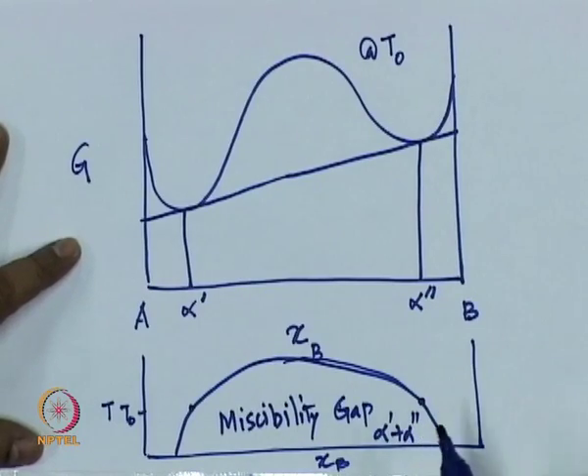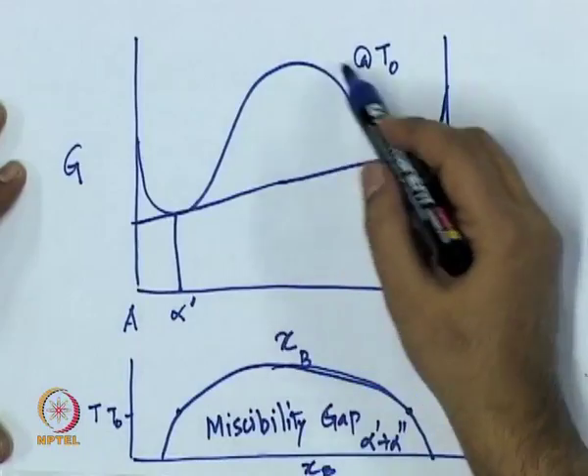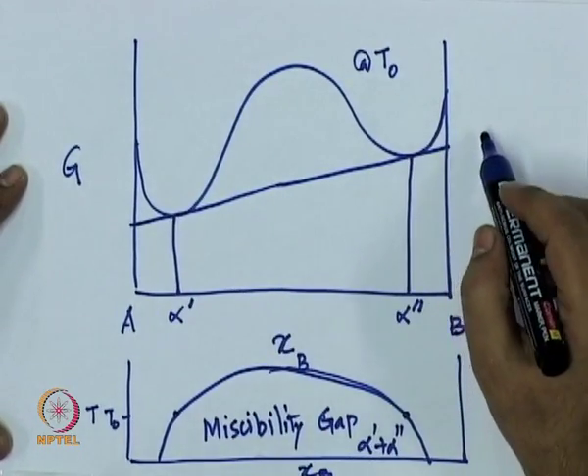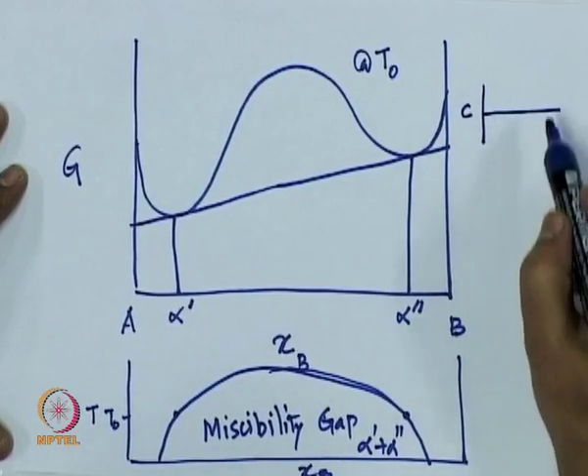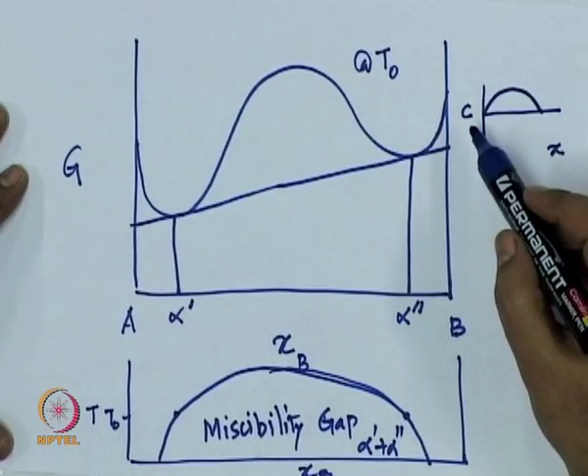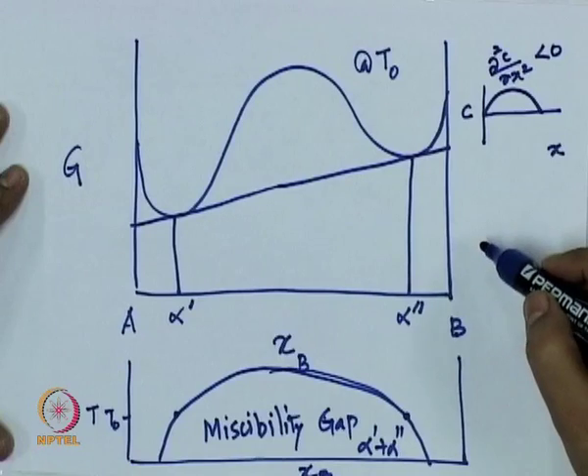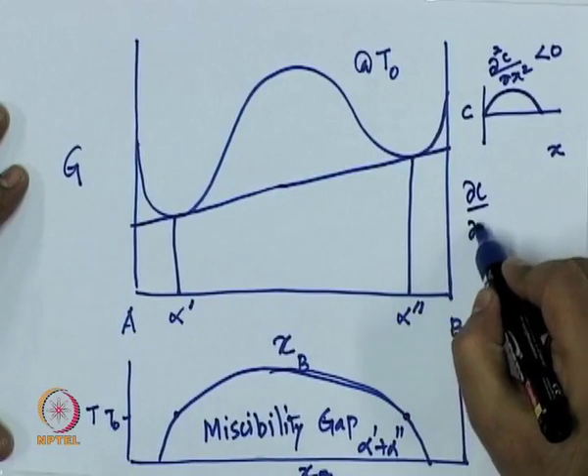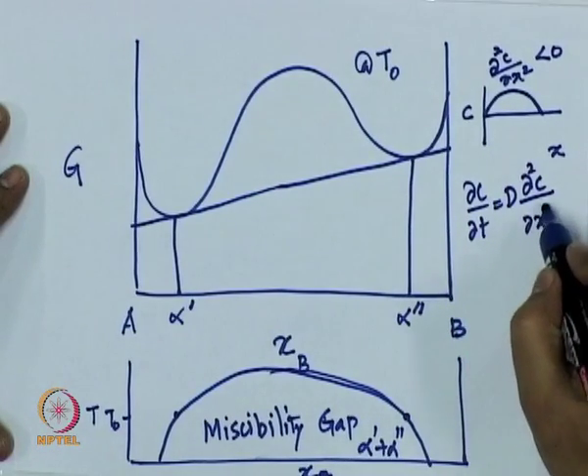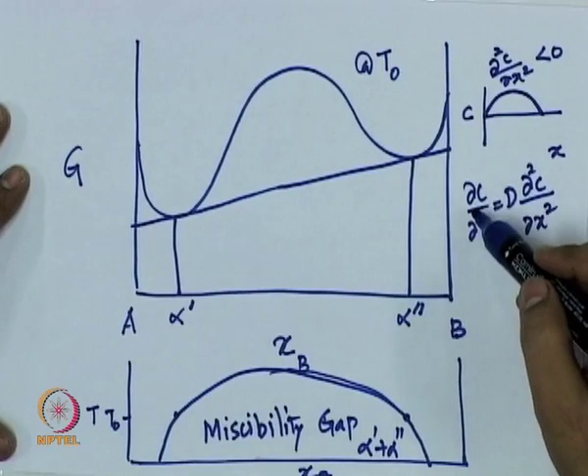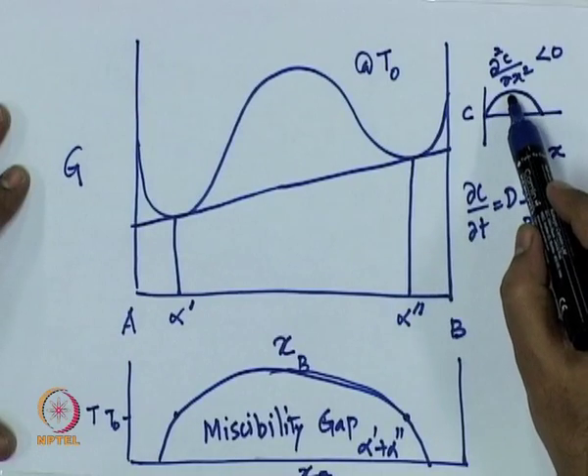Now, what is spinodal? We are going to describe spinodal and its physical significance. In the context of Fick's law, if you take composition as a function of position and the composition changes such that the curvature is negative, Fick's second law says ∂C/∂t = D · ∂²C/∂x², with D being constant and positive. This sign decides how composition changes with time — a region of negative curvature means the composition is going to keep dropping.